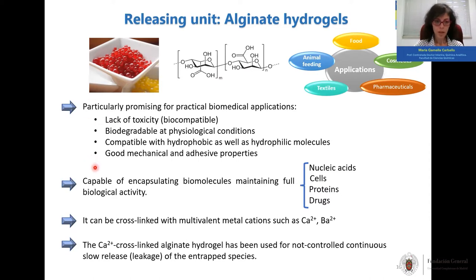It's possible to encapsulate a great variety of molecules, but the most important thing is that these molecules maintain their biological activity inside the hydrogel. It's very easy to prepare these beads because you just need to prepare a solution of alginate with the drug that you want to entrap in it and add a multivalent cation, usually divalent cations such as calcium or barium.